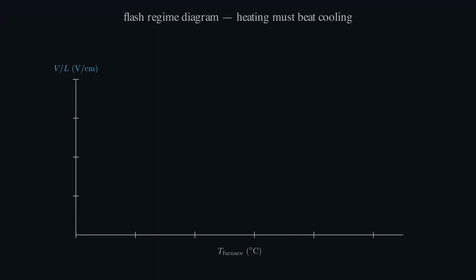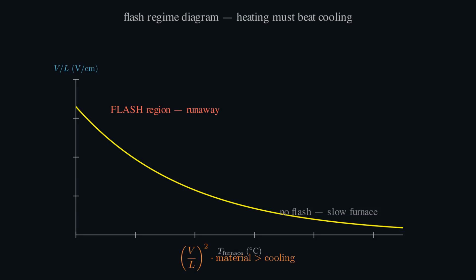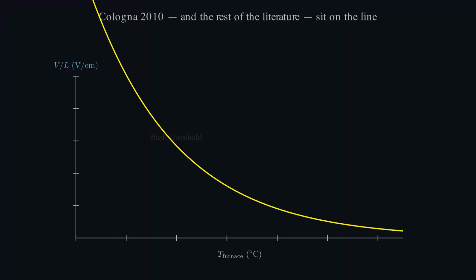Plot it as a regime diagram. Furnace temperature on the horizontal, voltage per length on the vertical. Above the curve, the flash region. Heat in beats heat out. Runaway. Below the curve, stable, dull, hours of furnace time territory. Drop in Cologna's 2010 data point. Zirconia, 850 Celsius, the voltage they used. It sits exactly on the boundary.